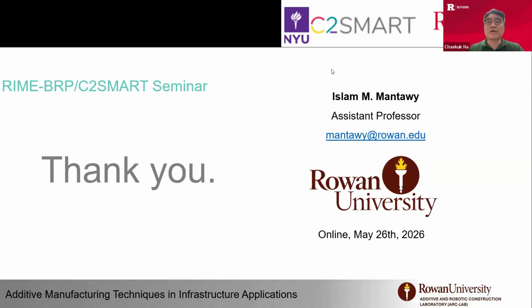One other question from the same attendee: is there any environmental or adverse impact when using it in marine or underwater environments, in the short or long term? Yes, printing offsite and placing it is very different from printing actively in the water, because you will have a lot of leaching. Whatever you have in the mix will be leached during the process. So most of the work we do, and that people are starting on, is to see how much leaching and washout you get that will impact the structure and also the marine life. We use pH and other tests to quantify it, and I think our material is doing well compared to the standard for water. Remember, what we did was in a limited water tank, so the concentration will be different from an open sea or open ocean.